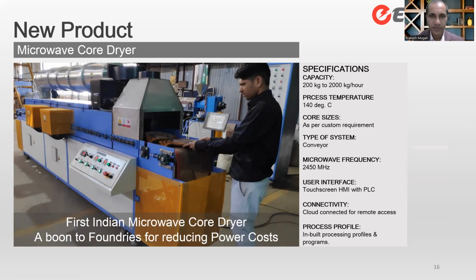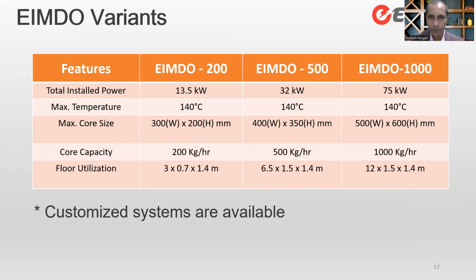Based on this demonstration, we recently installed a high capacity dryer of 1 ton per hour in a foundry in Belgaum. I'll share some photographs of the same. So what we have done is we've proposed three sizes of dryers. EIMDO-200 is a 200 kg per hour capacity dryer, EIMDO-500 is 500 kg per hour, and EIMDO-1000 is 1 ton per hour. We could definitely design larger scale machines if required, but what we've seen is that most foundries' requirements are covered in these three sizes.